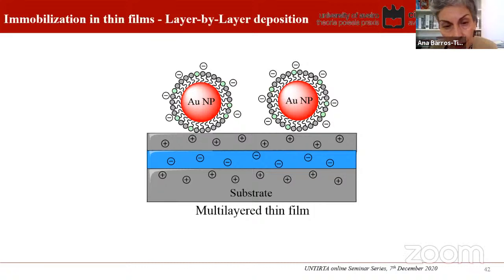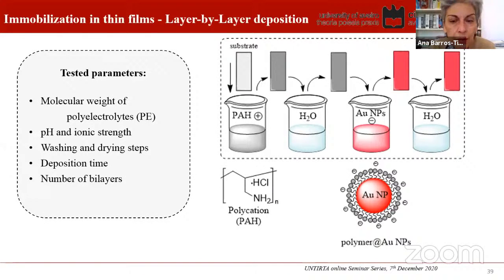So using a substrate, in this case actually glass, we deposited different layers of polyanion and polycation, and at the top we deposited the suspension or the colloid of our functionalized gold nanoparticles. So to achieve that, which is a well-known technique, the layer by layer deposition, we still had to carry out some studies, namely assess the effect of the molecular weight of the polyelectrolytes, the effect of pH and ionic strengths, washing and drying steps, namely the time between them, the deposition time, the number of bilayers, and so on.